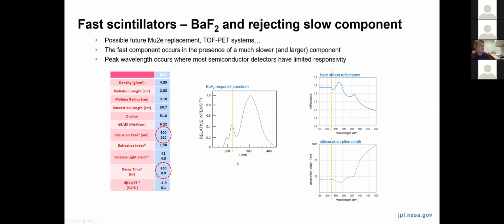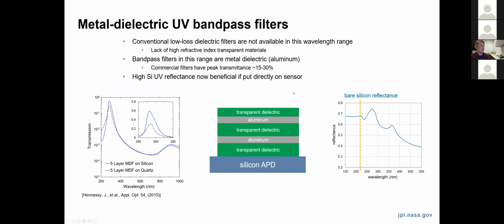So we wanted to know if we could create a bandpass filter that would reject that longer wavelength light. And this is done with multi-layers now of aluminum and transparent dielectric materials. This is in fact often how these commercial filters are fabricated in these wavelength ranges. Again, the more complex dielectric coatings are often not available as you move to wavelengths below 200 nanometers. And often their efficiency will be quite low.